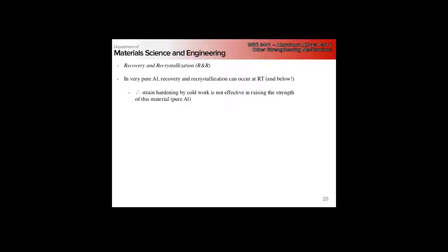Stacking fault energy, right? Aluminum, because of the high stacking fault energy, is very easy to cross-slip. So we have very high rates of dynamic recovery because dislocations can change slip planes, get around locks, right? And they can annihilate each other. Whereas in copper and nickel, other FCC metals, you can't do that. Remember when we talked about planar slip versus wavy slip during the very first section, right? Aluminum slip lines are crazy because the dislocations can move around obstacles. Right? So there was a question.